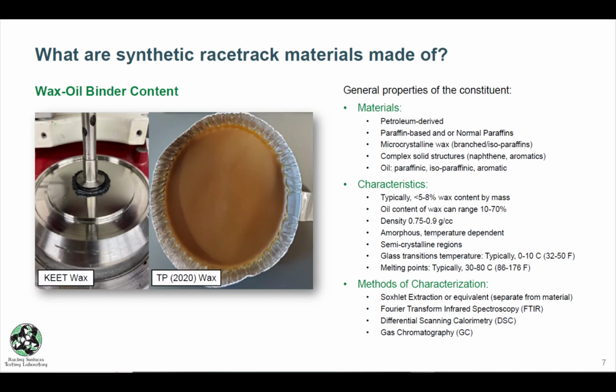And the wax, which is what we're going to be mostly discussing for the rest of this presentation. We know that it's petroleum derived, specifically that it's a paraffin-based wax. So you can think of it like your candles, so to speak. These waxes are fairly complex, but we can measure the total wax content present in the surfaces. With the newer tracks, I believe we're looking at generally less than 5%, but I have seen about 8% wax content on some of the race tracks. And these waxes have a large temperature range, particularly a higher melting point, but they can have different physical properties, which we're going to be talking about right after this.